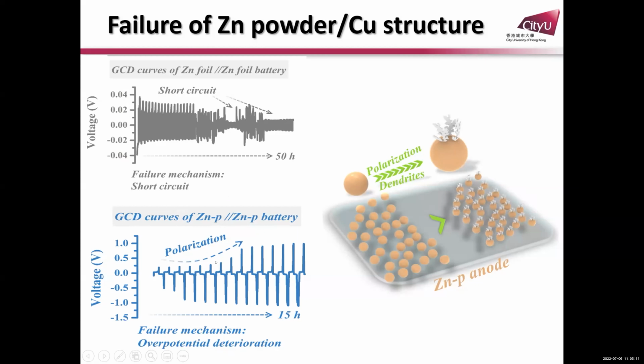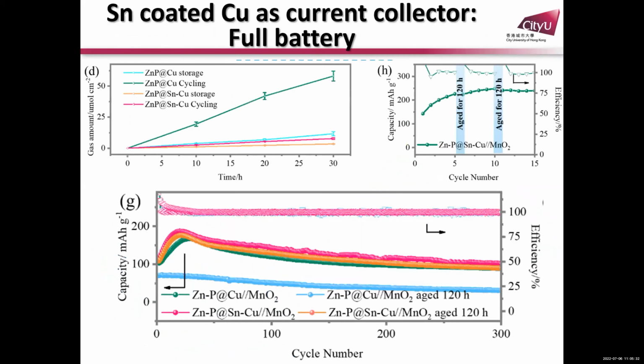It's not normally like you get a short circuit right away, but of course, if you keep doing this cycling, you still have a short circuit. But before the short circuit, the polarization gets much more severe because for each particle, you get something growing on the surface. The particles will separate from each other. The contact between particles, the conduction pathway, is broken.